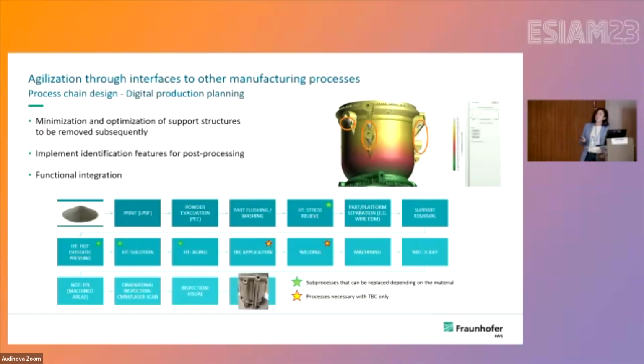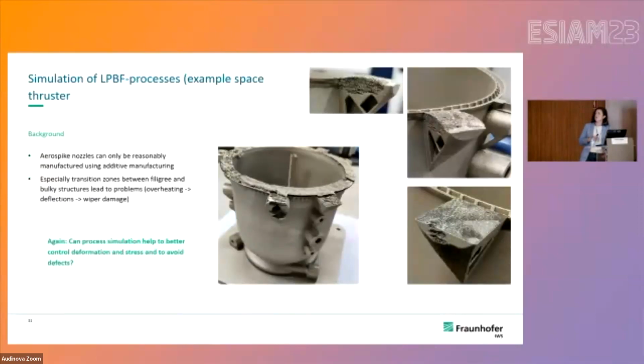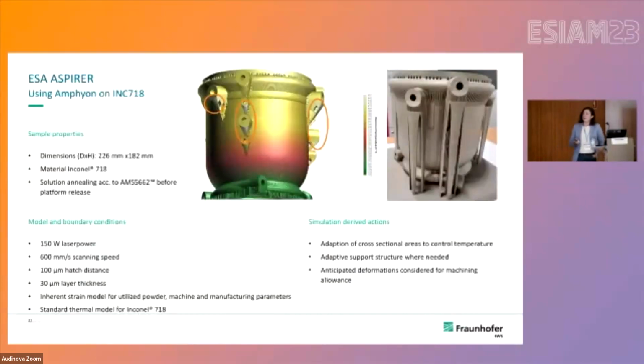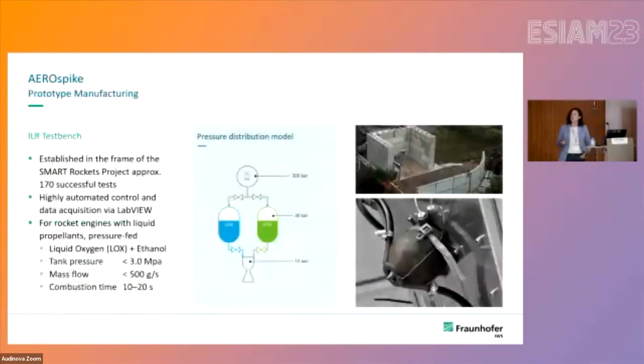Another issue for us is using simulation, in the third group I introduced to you, to avoid issues related to filigree structures before manufacturing, and if we are lucky, also to spare some of the steps in the process chain. So we introduce thermomechanical and also thermal simulation to see where we have critical thermally affected areas. We came out with this being the highest temperature, but these filigree structures are very dangerously affected by distortion and also lack of fusion and so on. And this process simulation helped to better control the deformation and stresses, so we could save time, whereas in the past adaptive support structures were needed to avoid these deformations. So it's a step that I would also recommend to you if you are working with such parts or applications.